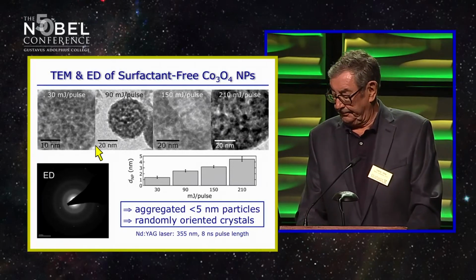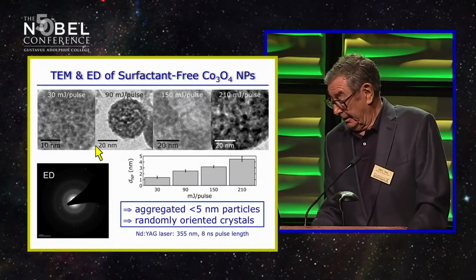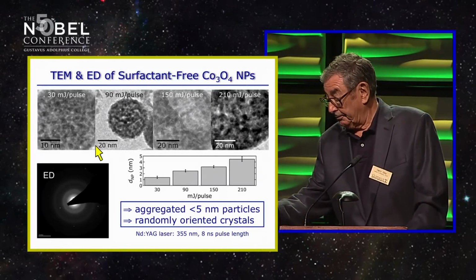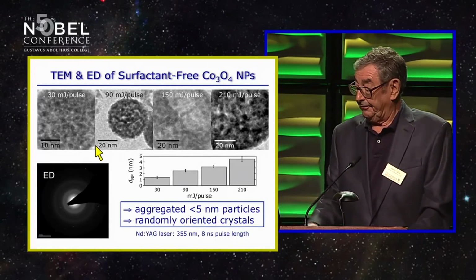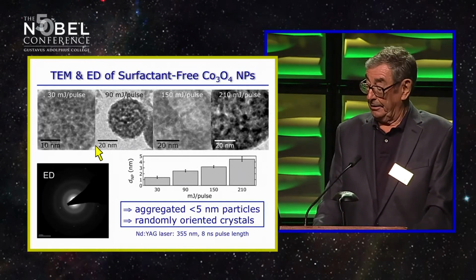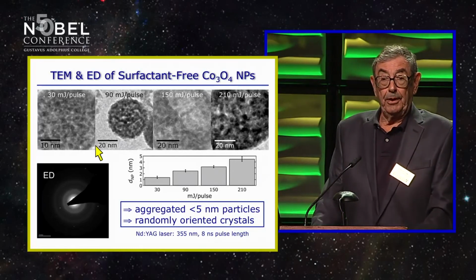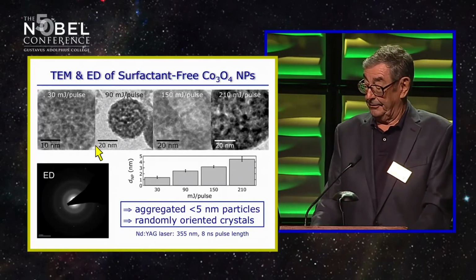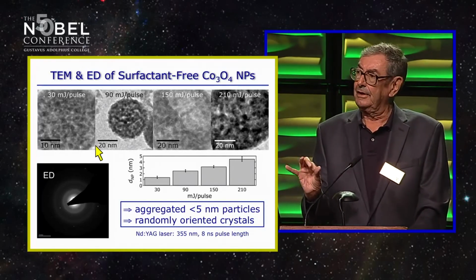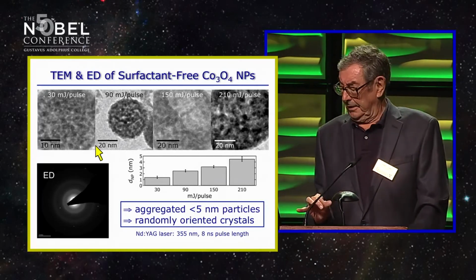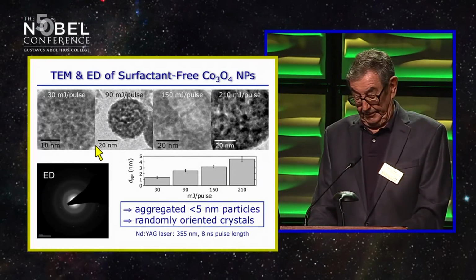For example, with a 90 millijoules per pulse, we can get a 2.5 nanometer, very regular nanoparticle. With higher pulse energies, we go to higher nano. So we can tune the size of this nanoparticle with pulse energy and pulse width.